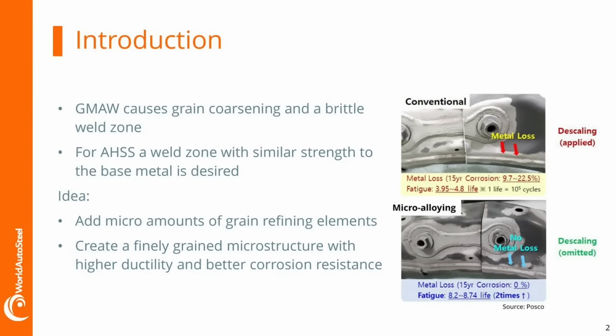On the right, we have an example where we welded at the top with a conventional filler wire. This leads to relatively severe material loss in an accelerated 15-year corrosion test, and also a certain fatigue life here with a maximum of 4.8 lives, or 10 to the power of 5 cycles. We also have to descale the weld after welding because there's slag on it,